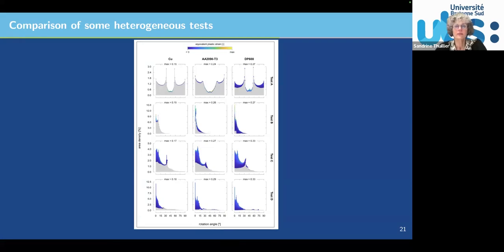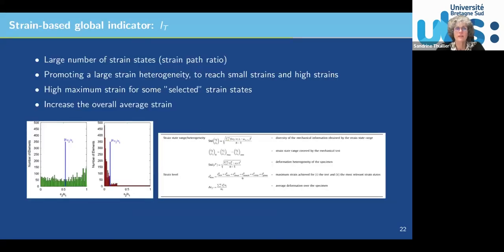So it can tell you whether the test is mainly centered in the rolling direction, in this case 0, or whether you have a better distribution. In this case you can see something more distributed, so maybe you will be better able to characterize an anisotropy with such a test compared to this one. From this material information, you can build an indicator, for example, this strain-based global indicator.